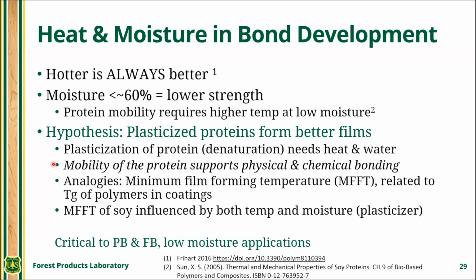Or whatever matching chemistry to find each other to develop a stronger network. So that mobility of the protein during bond formation is the way that you can improve the protein-to-protein interaction, independent of the cross-linking agent you're using. Analogies: minimum film forming temperature in coatings. Same thing, that's related to the Tg of the polymer in the coating. If you're below the Tg, you don't form film. And I think you have this similar thing going on with the proteins.